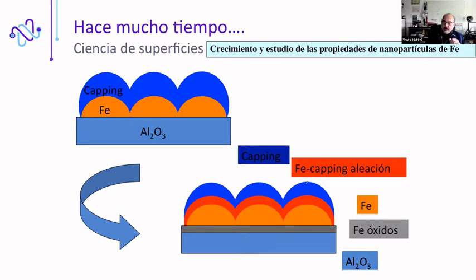And that was very frustrating for us because what we wanted, what we needed for our, let's say, fundamental studies is a simple system that we could understand. This system that we created is extremely complicated. We have a gradient of oxygen inside the iron nanoparticles, and it's very hard to simulate the magnetic properties. So we came to the conclusion that we needed another way to fabricate nanoparticles.